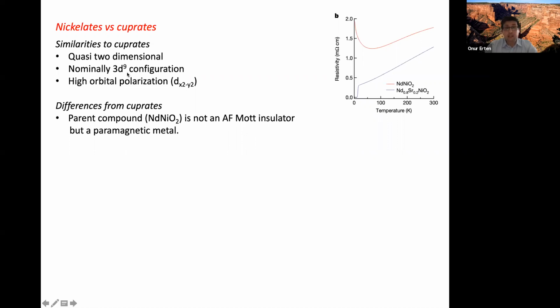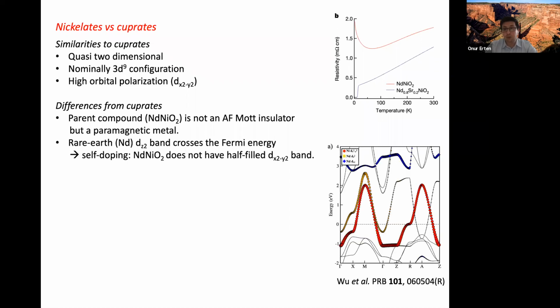So the parent compound is not an antiferromagnetic insulator, but a paramagnetic metal. And this is very strange, because if it is really 3d9, if it is a half-filled band, you would expect it to be an antiferromagnetic Mott insulator. How is it that it's not an antiferromagnetic Mott insulator? And here comes the main difference from cuprates.